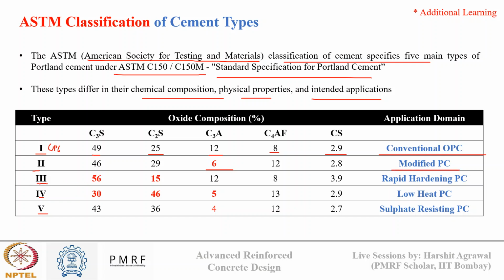Okay, so that's why this type of cement is called modified Portland cement. Then in type 3 cement, compared to type 1, we have higher proportions of C3S and a lower proportion of C2S. What does this cause? So C3S has a higher rate of reaction and C2S has a slower rate of reaction. So more C3S will make cement rapid hardening, and thus this type of cement is known as rapid hardening Portland cement because it has more amount of C3S in the system.